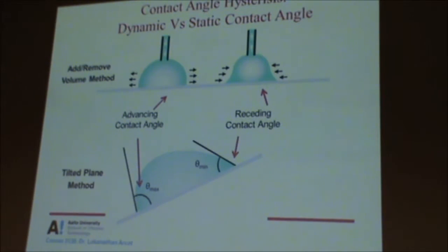Receding is, let's say you take the same situation where you're taking the liquid up. Now as the liquid goes inside, it buckles here, and then it becomes thinner and thinner. The water droplet collapses. Okay, so the contact angle keeps decreasing, and finally it's so low that it jumps from this point to this point. Okay, is the pinning mechanism clear? Okay.